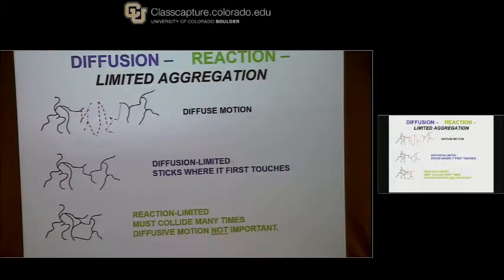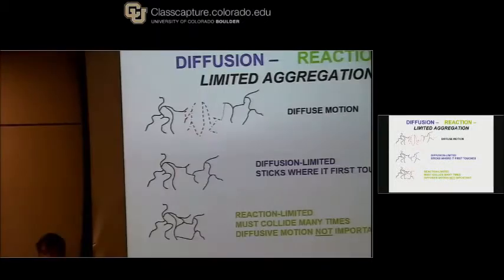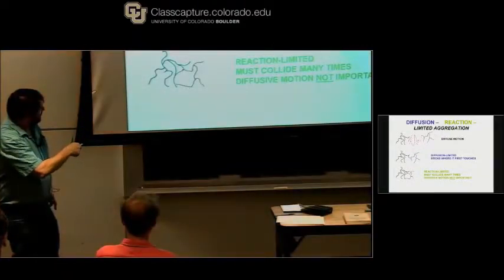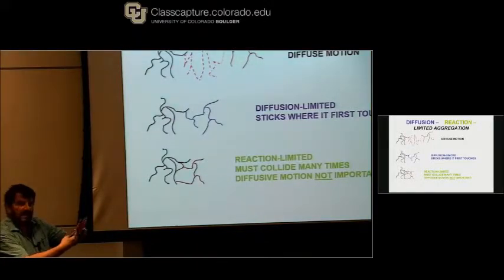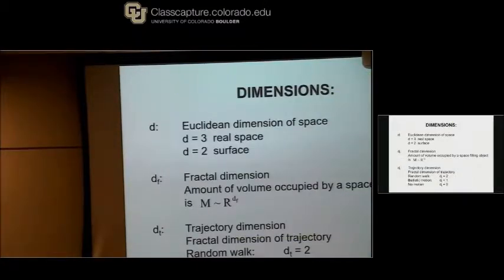It cannot go in because it's diffusing. It's going to explore all space, and it's going to hit somewhere on the outside much more rapidly than go on the inside of these arms. But if it doesn't stick, then diffusion can allow it to come in closer. And that's going to lead to a higher fractal dimension.